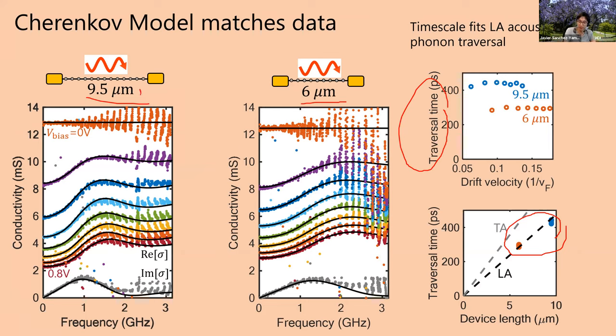And so what's nice is that we have data on two different size samples. We can extract the time it takes for the phonons to go across the sample, and it matches very well with the velocity of a particular acoustic phonon mode, the longitudinal acoustic phonon mode in our material. So it seems to match up that this is a process by which phonons are being amplified across our device and then they're traveling down.